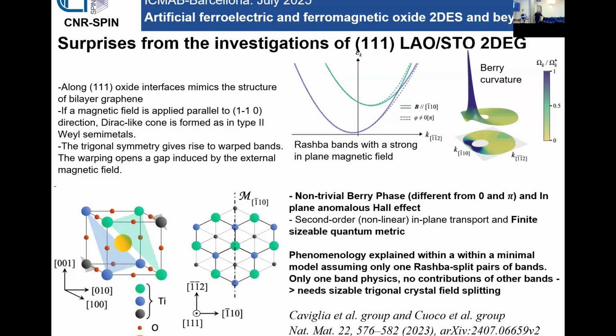Now, why are these 111 heterostructures interesting? Because if you look at this perovskite along the 111 plane, the surface has essentially a hexagonal symmetry, and the system is similar to bilayer graphene. This was already observed some years ago. There was a Nature Communications paper suggesting that many perovskite oxides can host exotic physics if grown along the 111 direction. More recently, there were in particular two papers from the Caviglia group, which studied the non-magnetic 111 LAO-STO 2DEG, and they found very interesting properties.